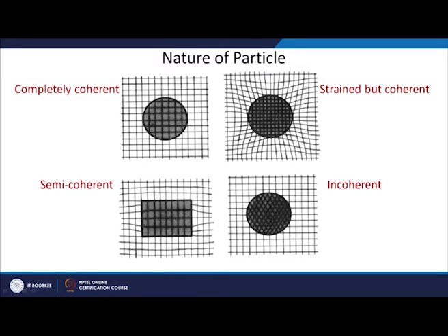You can see that there is a strain in the matrix around the precipitate. In the precipitate we have made the grid finer, and the grid in the matrix is a little bit coarse. So the lattice parameter of the matrix is more, and the lattice parameter of the precipitate is less. So you can still maintain the coherency, but you have to have some kind of strain. I have to stretch the bonds and so on to maintain the coherency. Depending upon whether the precipitate is soft or the matrix is soft, the strain will be accommodated in that particular phase. In this case we are assuming that the matrix is soft in comparison to the precipitate, so you can see the whole strain is accommodated by the matrix. Now sometimes it may happen that this material is highly strained, so it does not want to be in that strained condition.